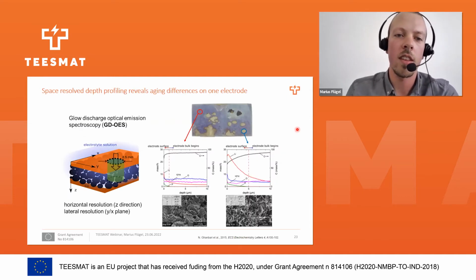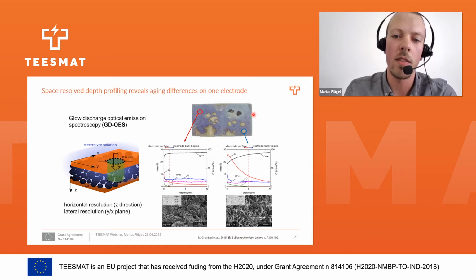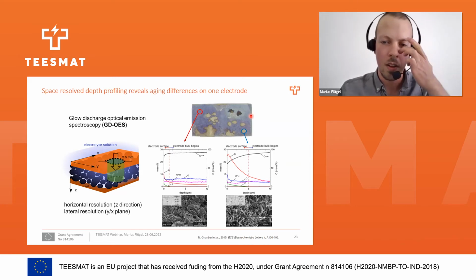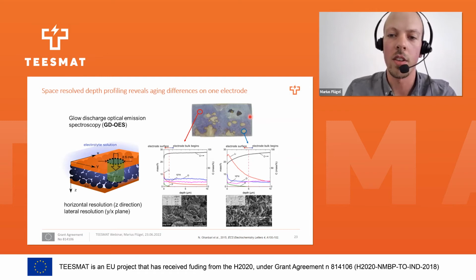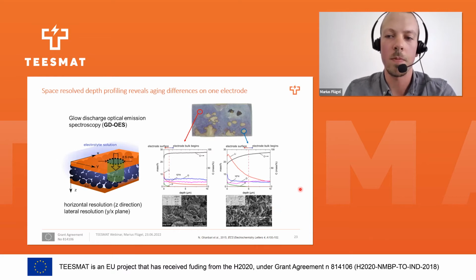We can even see different aging mechanisms on top of one electrode. Here you can see in the photograph of such an electrode, the blue area exhibits strong SEI formation, whereas the golden area shows lithium plating on top of the anode. This can also be verified with SEM images.